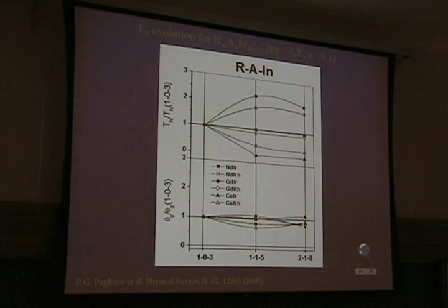So that tells you, at very high temperature, when the crystal fields are all populated, and you make an average of your data to remove anisotropy, a measure of the effective magnetic interaction at high temperature, right? So when you do that, you normalize for neodymium, gadolinium, and cerium, that are all antiferromagnetic.